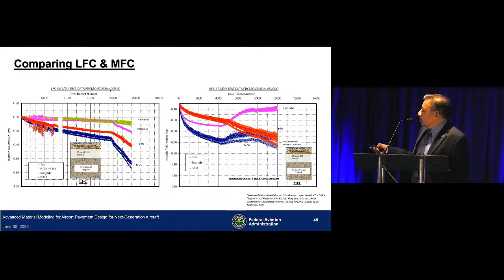Remember these two sections, this is medium strength with conventional aggregate base, and this is low strength subgrade with conventional aggregate base. And I have shown here the pavement cross sections. So for low strength, you have 36 inches of sub-base and 8 inches of base layer. So you're looking at 44 inches of aggregate material that is stress hardening. What you see on the medium strength is 12 inches of sub-base and 8 inches of base layer. So you're looking at 20 inches of stress hardening material. So almost half the thickness compared to the low strength.